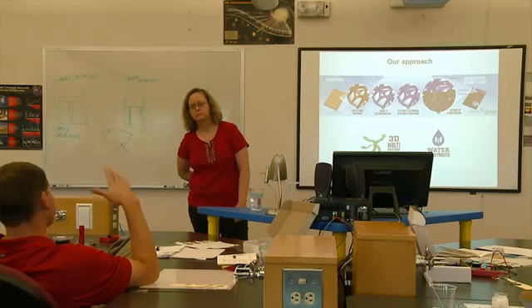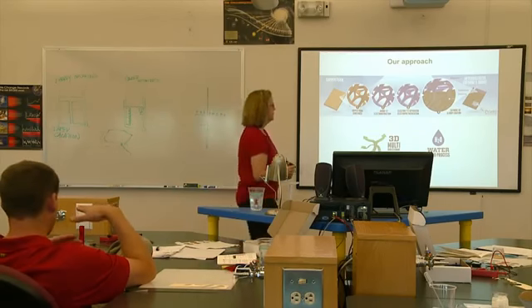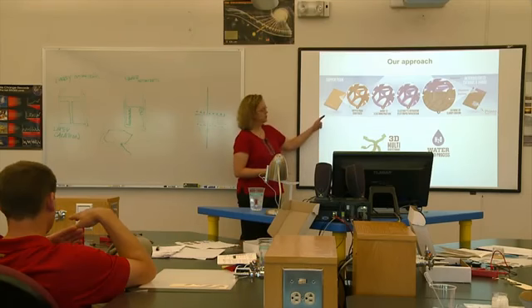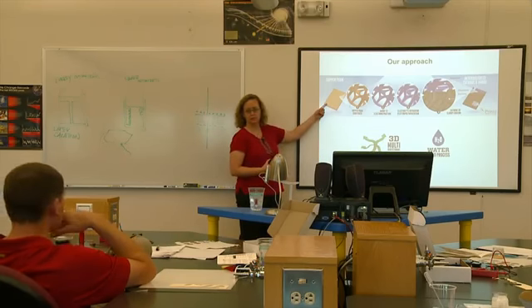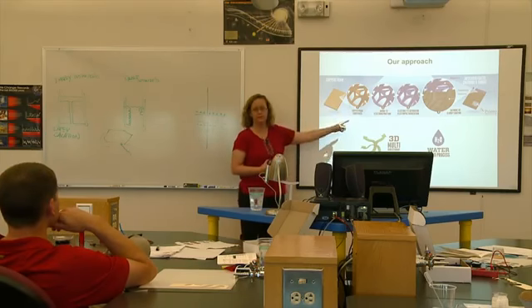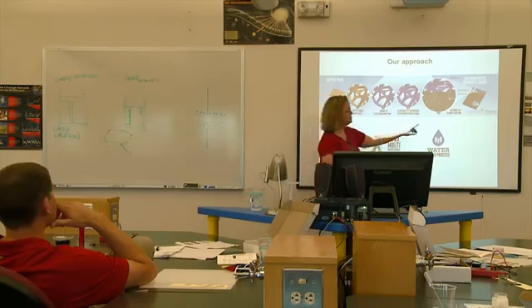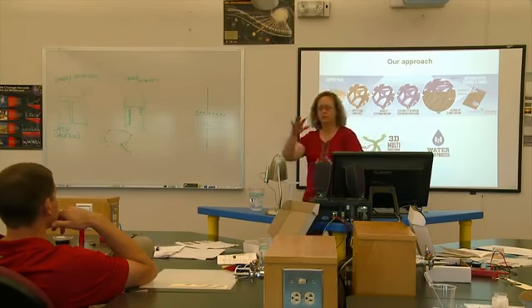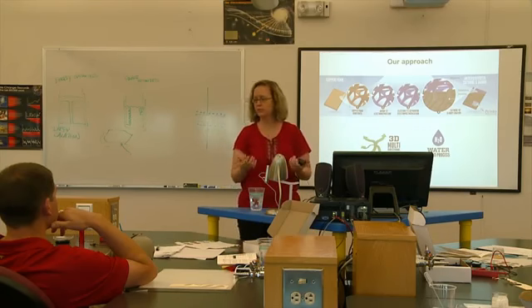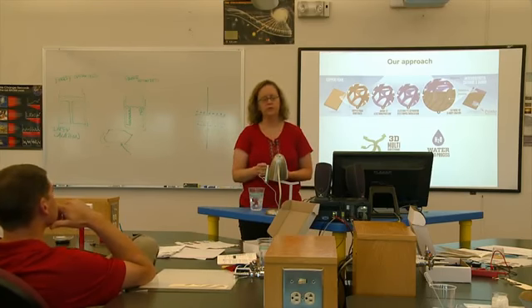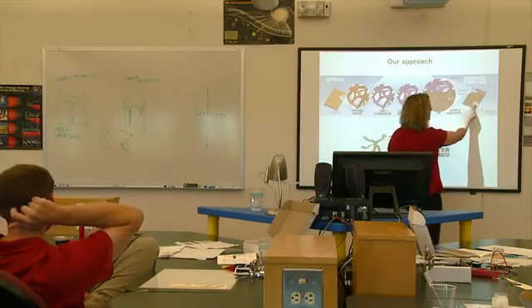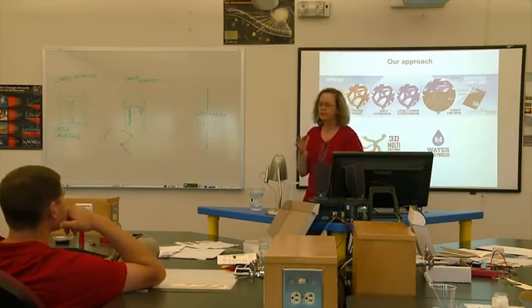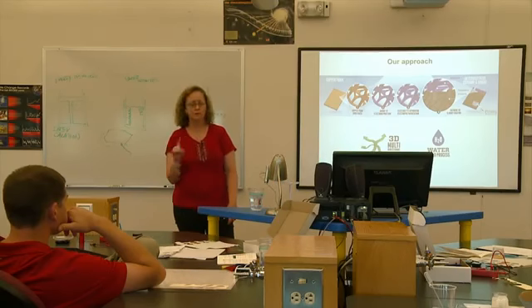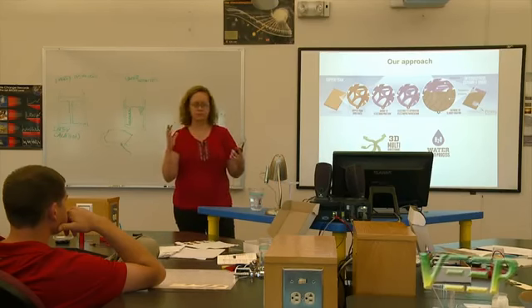Yeah. So at some point in there, then you connect a lead to the copper sponge and the outer surface of black. Yeah, actually, what this picture is not showing you is we first put a contact here that we ultrasonically weld, and that is the contact that we use for all the plating, and then it stays as the contact at the end. And then at the very end, we put an aluminum mesh, and then we put the black ink stuff on top of that also, and it dries, and those are your 2 contacts. So we don't know that our contacts are in the perfect spots yet. Here I'm showing you in this little cartoon, one of them here and one up here. But the National Renewable Energy Lab has amazing equipment to test batteries, and they have a modeling group that will generate a computer structure of your battery and tell you what should happen over cycling.